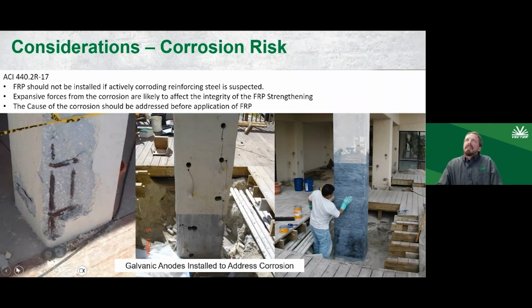Considerations in corrosion risk. So for instance, if we're looking at this situation here, on the left, we have a column where we can see active corrosion going on of the reinforcing steel. In that middle photo, they've installed a type 2 anode, a galvanic anode to mitigate that corrosion. And then you've got the technician on the right installing the FRP fabric. What we don't want to do is have active corrosion going on, wrap that structural element, and then that corrosion still keeps perpetuating, and we've got spalls and delaminations of the surrounding concrete. It's a big deal, and what happens is that if there's fracturing going on inside of that column because of active corrosion, that carbon fiber isn't participating fully within that structural element.